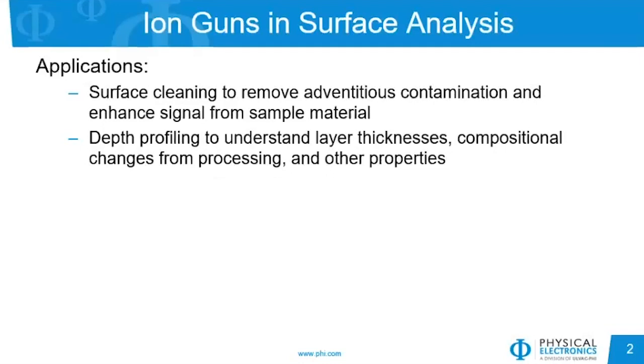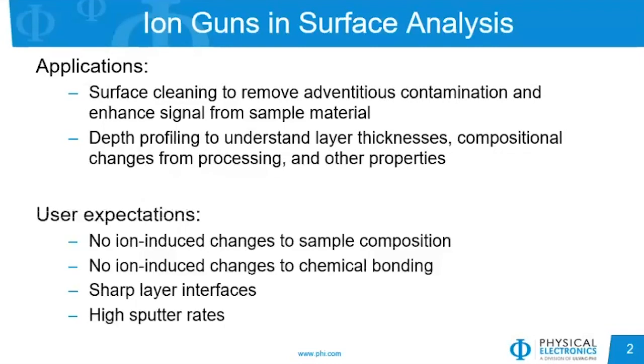And so when we do these types of processes with ion guns, what are the expectations that ideally a user would have for these materials? What we would like to see is that the ion beam induces no changes to the sample's composition, no changes to the chemical bonding states that we wish to analyze. We would also like to maintain sharp layer interfaces, and we would also like to be able to do this at high throughput with high sputter rates.